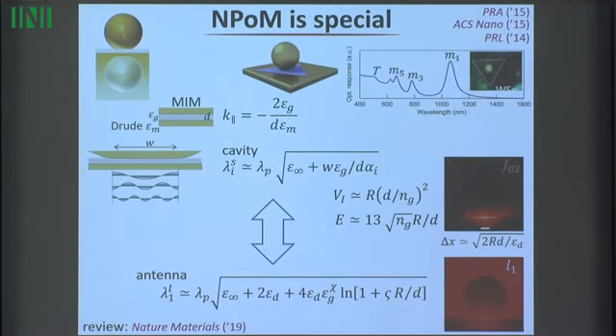We actually understand quite a lot about this mode description from classical electromagnetism. It is difficult, however, to do the simulations because I have to worry about discretizing space when I'm doing these simulations for these modes. That gap might be 0.9 nanometers, so then I have to discretize space on a 0.1 nanometer scale, which is less than the size of atoms. And so now we start to worry, is this valid for electromagnetism? Am I in the right limits here?